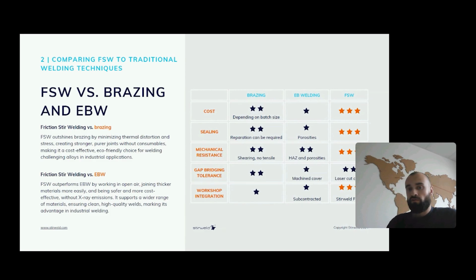Then if we look at the gap bridging tolerance, it's almost the same for electron beam welding and brazing, because those two processes need very tight gap bridging, as in electron beam welding, the fusion is performed only between the two edges of the parts to be welded, so no gap is allowed. And in brazing, the filler material needs to have a good contact on both parts, which also requires a tight gap bridging. In friction stir welding, we also have a tight gap bridging requirement, but usually a laser cut part is accurate enough, because we do not add any material in the weld either, and the rotation action of the tool allows closing the initial gap between the two parts.